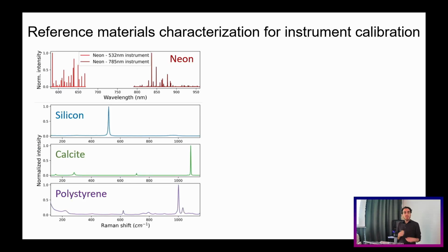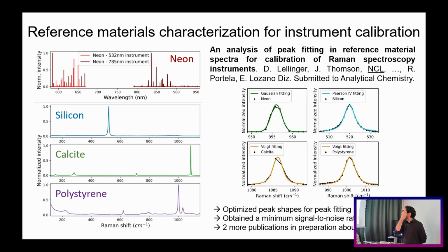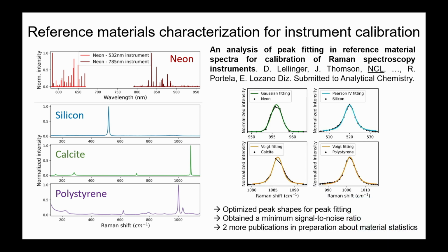Then we were looking at different materials for calibration, and we chose some others: neon, silicon, calcite, and polystyrene. The first thing we found in our interlaboratory study is that the peak shape affects the peak fitting a lot. So we were able to recommend specific peak shapes for the different materials, and also come up with a minimum signal-to-noise ratio necessary for this to work effectively.